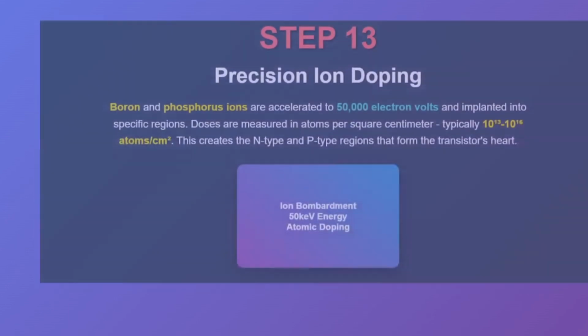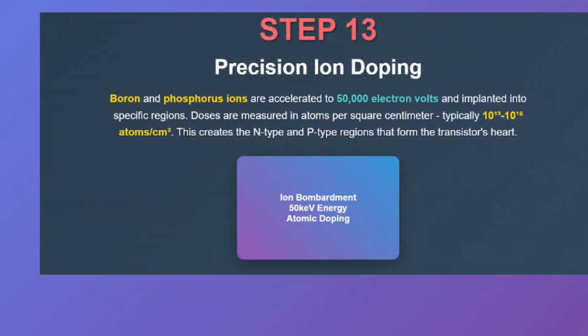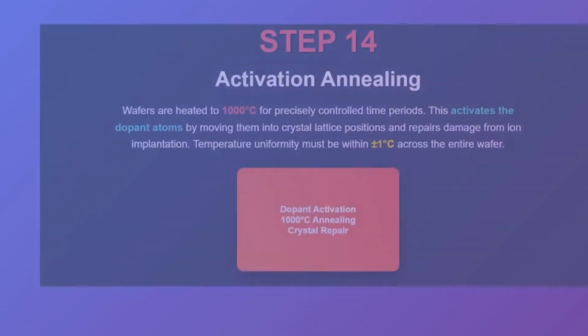Step 13. Ion implantation. Dopant atoms like boron or phosphorus are accelerated and embedded into the silicon at energies up to 50,000 electron volts. This forms the N-type and P-type regions essential for making the transistor function. Step 14. Activation annealing. The wafer is then heated once again, typically to around 1000 degrees Celsius, to activate the implanted dopants and repair any crystal damage caused by the ion implantation.